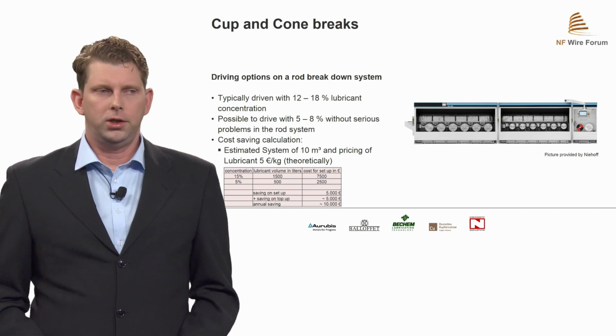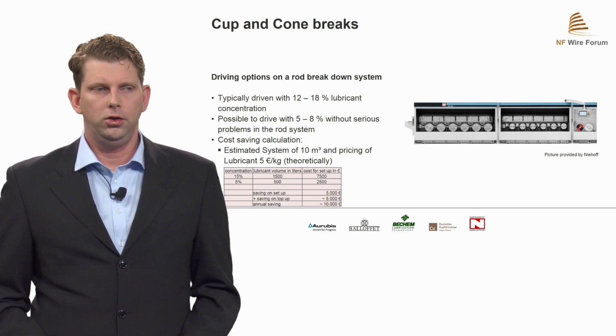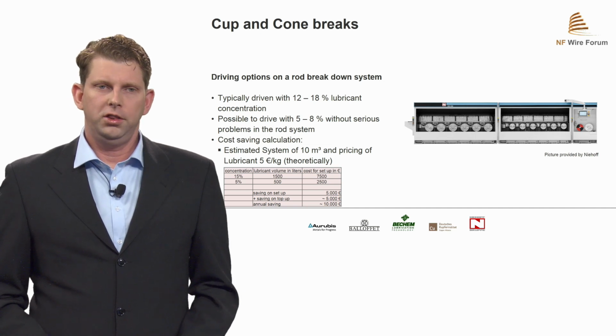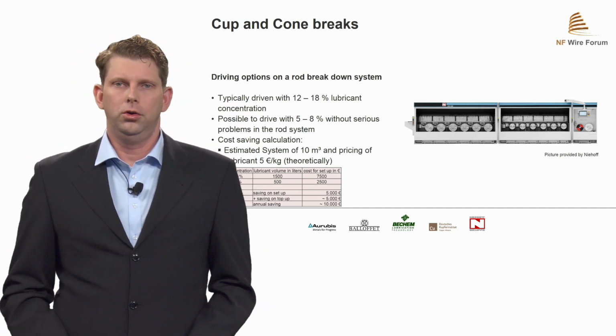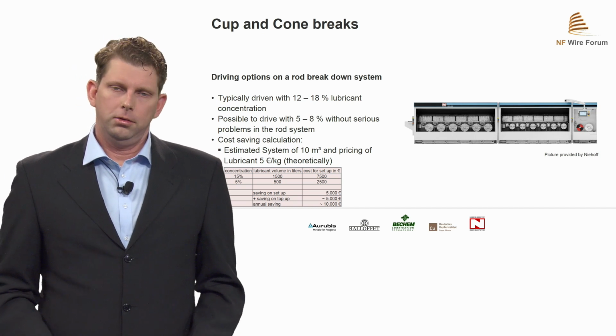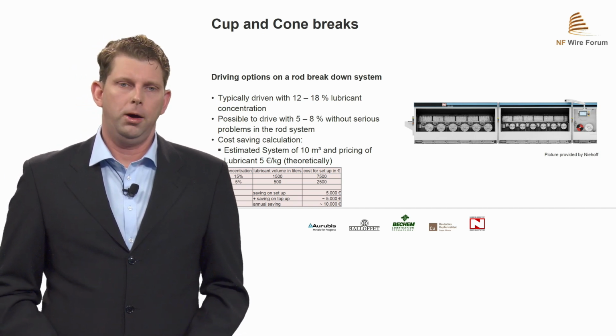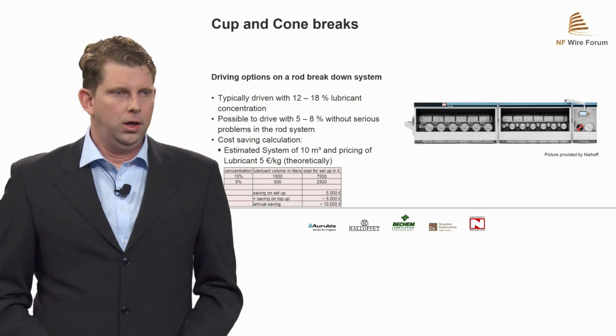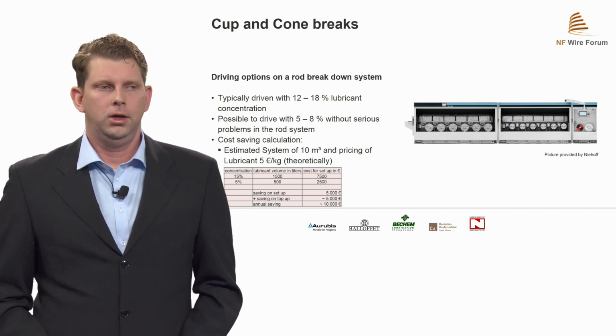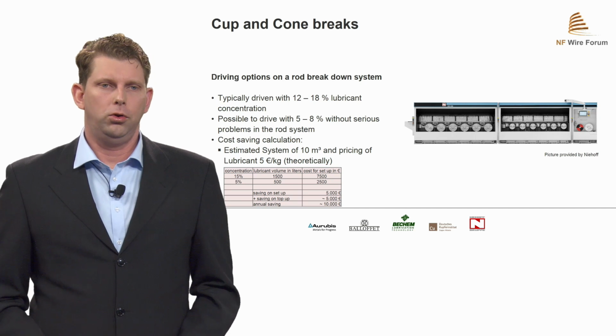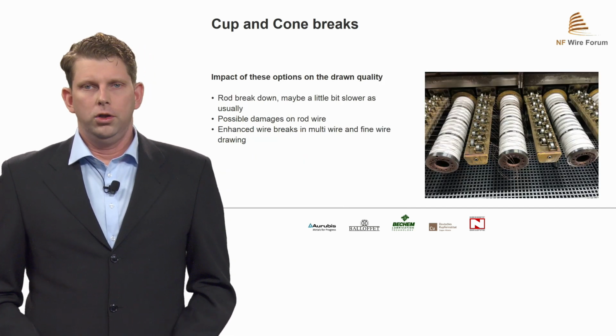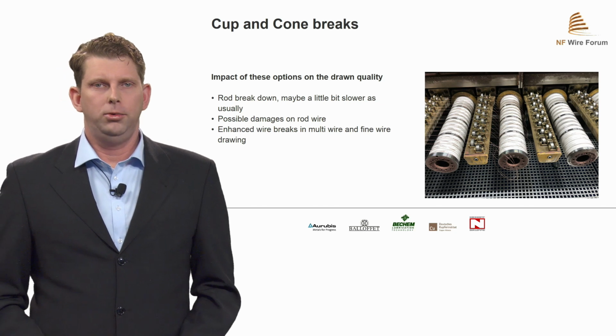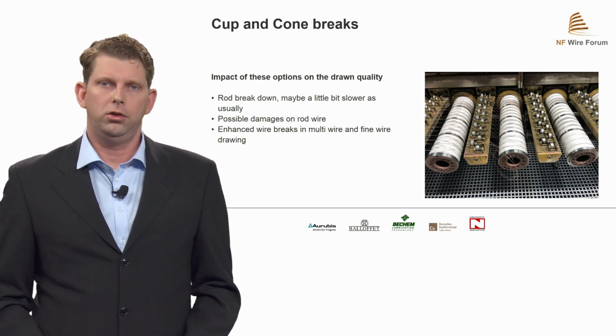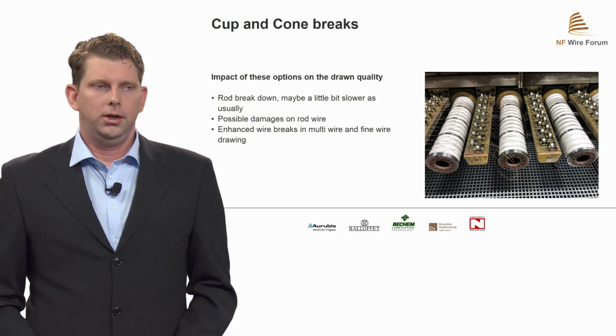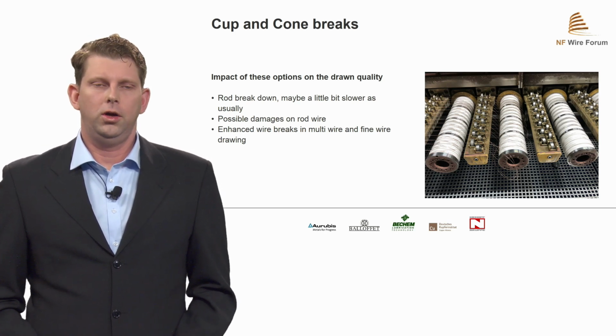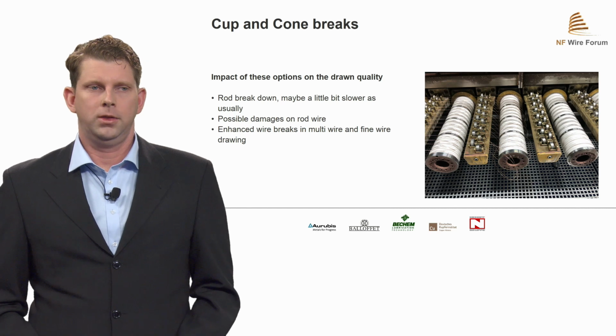If we do the same with the 5% concentration, we have 500 kilograms and €2,500, which gives you a saving of €5,000 estimated. Plus maybe another €5,000 over the top-up time for 1 year driving, would be €10,000 in total. But what does this mean for the drawing process itself? First of all, your rod breakdown system maybe has to be driven a little bit slower. Normally 25 to 30 meters are possible. Now you can only drive 20 meters, for example. So you have a reduced production capacity.